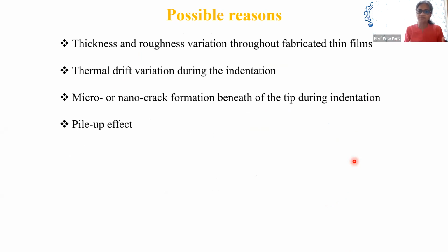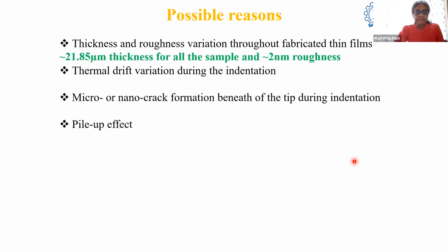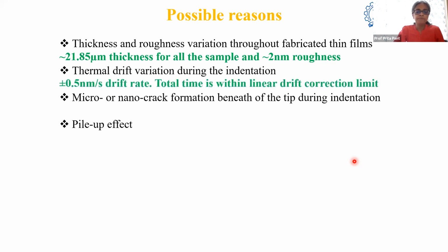So maybe there's subsurface cracking which we can't see, and that's making it effectively more compliant. Or maybe there are pileups in the softer sample, which are giving complications. So we set about confirming or denying them, and the thickness was okay, roughness was low, drift rate in this case was low, but like I said, I would still like to talk about this. And the total time of the experiment was within this linear limit, which I'll talk about.